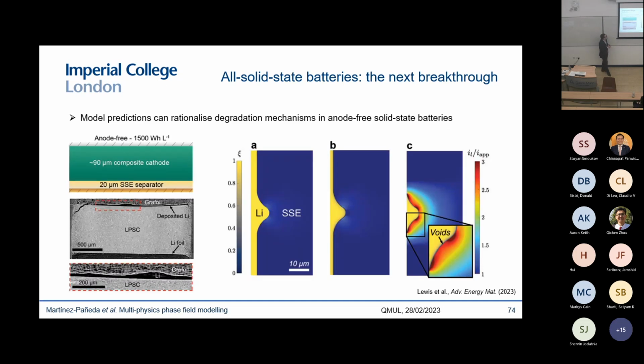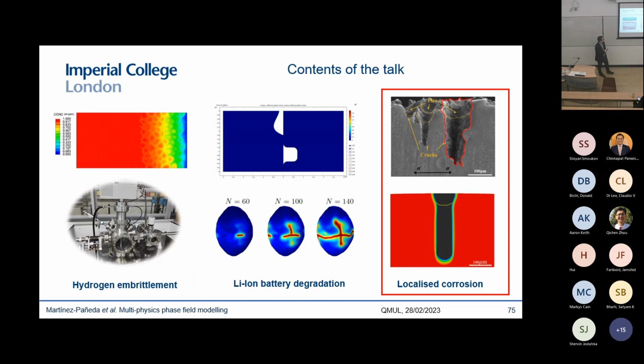And we've also looked into anode-free solid-state batteries, and this is work in collaboration with Matt McDowell at Georgia Tech. He's doing very nice work on anode-free batteries, and very nice characterization and imaging work. We used our model to confirm what the experimentalists hypothesized, which was that the uneven plating and stripping that you get in anode-free solid-state batteries was responsible for the degradation mechanisms that we're observing, for the early short circuit of these solid-state batteries. And this is what we see with our model as well. You can see that these protuberances, or this non-uniform plating, easily lead to the nucleation of voids and these highly localized currents there.